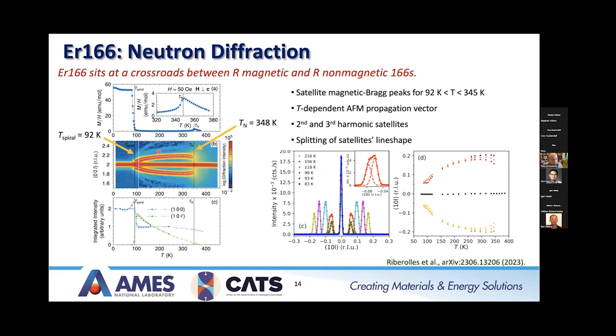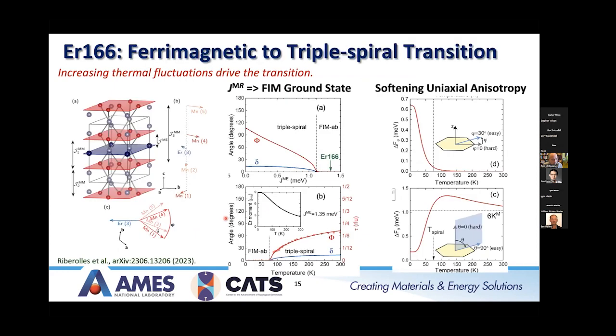The other feature we've been looking into is that if you look at the diffraction pattern here in the middle, you see the primary satellites, but then you also see peaks corresponding to about 2 tau and 3 tau. For magnetic diffraction, you may expect a 3 tau peak if you're getting a squaring up of the antiferromagnetic structure, but the 2 tau peak is more anomalous. Right now we're broadly associating the appearance of these multiple harmonics, and also the splitting here, with some kind of subtle distortion to the magnetic structure.